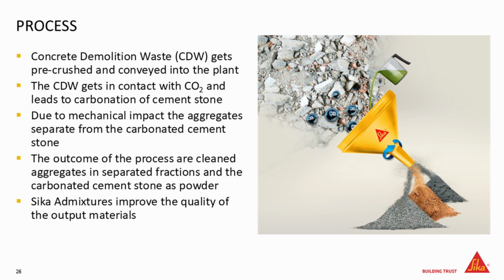Our process, I show you later a video of this, is basically a big ball mill. And into that ball mill we put the concrete demolition waste, and we drive the ball mill not in a way that it's usually driven, because usually it's driven to mill something down. We don't want to mill it down. We want to introduce a lot of friction, so that we separate the nice stones from the cementitious parts. So it's basically like a steel brush, we want to clean the aggregates, because we want to take out the primary aggregates and give them the properties back that they had at the beginning. That's the idea of the process.